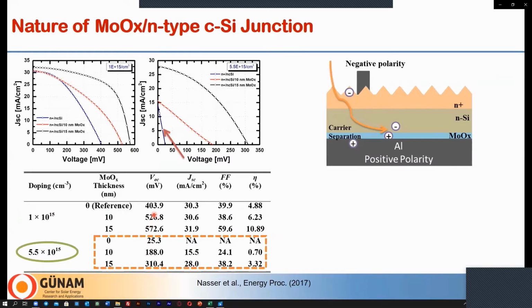Now, if we look at the device which was prepared with a highly doped wafer, we see that the device without molybdenum oxide here, so just silicon, didn't show any diode behavior, because when we increase the doping concentration, it results in a thin depletion layer width between aluminum and silicon, across which generated electrons and holes can tunnel, which results in a rather ohmic behavior here. Now, after inserting molybdenum oxide, both with 10 and 15 nanometer, between aluminum and silicon, it didn't lead to much enhancement in VOC. So we have the highest at 310 millivolt, and the overall performance is very low compared to the cell which was prepared on lightly doped wafer.